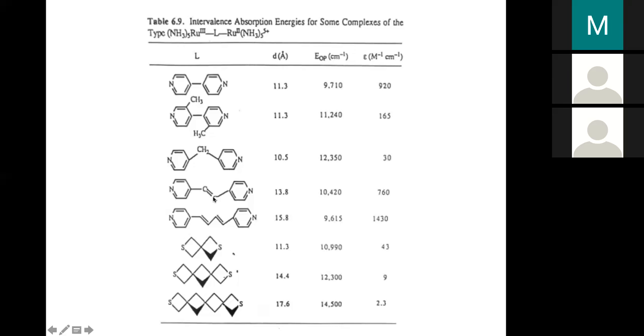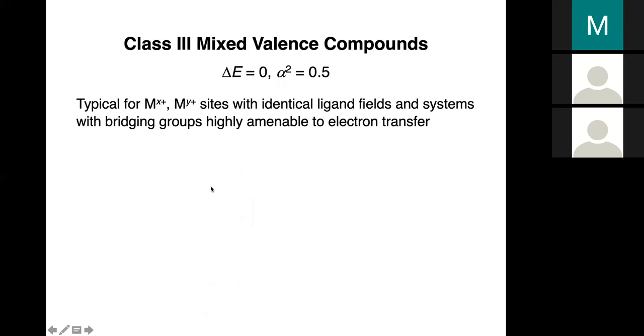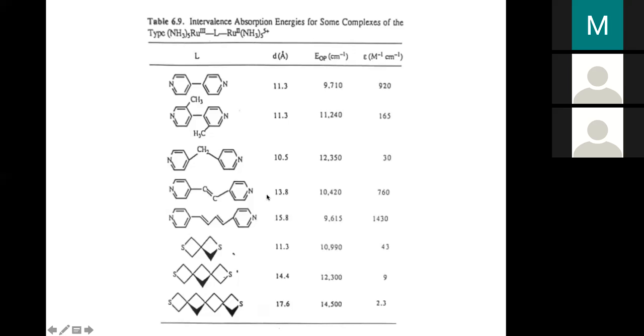If you have an ethylene, a carbon-carbon double bond between the pyridines, this can provide a conjugated pathway. So here, even though the metals are further apart, we can get stronger mixing of the states. And here's an example: if you add another carbon-carbon double bond into the ligand, this is even easier to reduce. You have a more accessible orbital pathway. Even though the metals are further apart, you get greater mixing and a more intense MMCT band. And then at the very bottom, you see these sulfur-based bridging ligands. And these are quite poor at transmitting electrons. And you can see the longer those get, the weaker the mixing between the states.